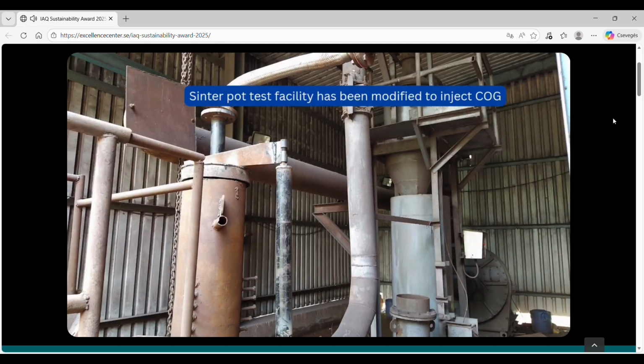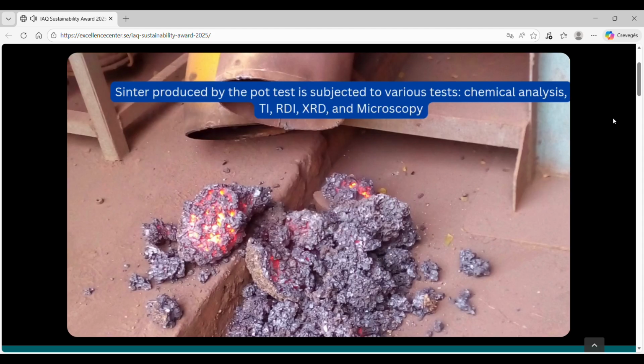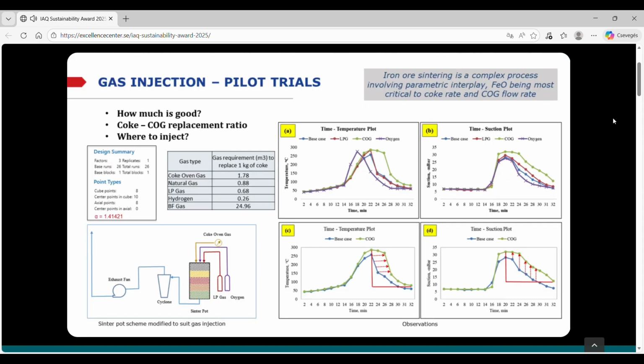The pilot trials began in 2019 using sinter pot facility. It did not have arrangements to inject gases, so we introduced gas injection system and conducted trials. The product sinter was dense, had higher strength, and better elevated temperature properties. Due to parametric interplay which is inherent to sintering process, the alpha in the design of experiment showed 1.4.